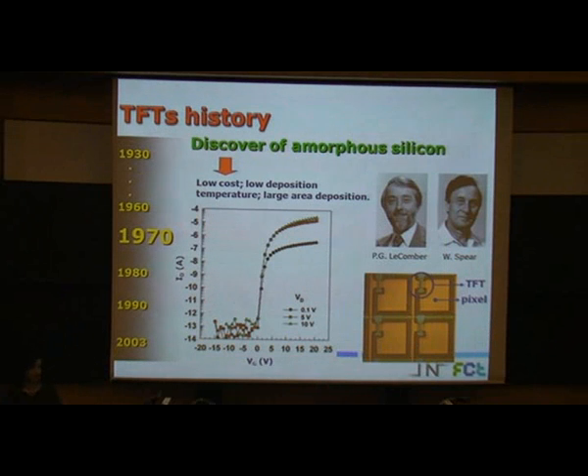Only around the 70s, because more or less during this period liquid crystals appeared, and also due to the need for larger displays, and also due to the proof by Professor LeComber and Professor Spear at Dundee University in Scotland, they showed that it is possible to dope amorphous silicon and use it as a true semiconductor. And they produced the first amorphous silicon TFTs. This is a typical transfer characteristic of amorphous silicon TFTs, where you can see that the on-off ratio is very high. We can switch the device from an off state of 10 to the minus 13 amps to some tens of microamps in the on state. The swing voltage is very good, and also the turn-on voltage is very low.